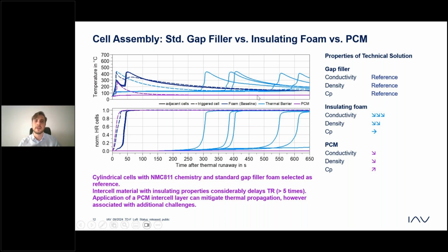Last but not least, also a phase change material, which is represented in purple, and this one also has, compared to our reference, a lower conductivity and lower density, but a higher CP value. What we can see here is that at least for our duration here, we see no thermal propagation, so the neighboring cells are not seeing the thermal runaway in this case. Phase change materials are in this case very interesting, but they come with additional challenges like the price, and also the packaging must be changed. So regarding the efficiency of the battery, we have to find a compromise here.